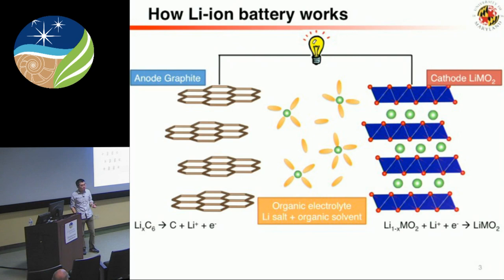So that's one of the mechanisms. The second is that you may have some side reaction. As we showed here, in a solid state battery it's very favorable to have reaction between electrolyte and electrode. In the real commercial electrolyte, the same thing also happens. For example, in the earliest generation of the Nissan Leaf, if they are in states like Arizona, which is super hot, the battery life dies very quickly, like in 2 years. That's basically too hot, so the reaction is accelerated. There were actually some lawsuits there. So as I said, anything that fails will give you failure. There are so many things that can go wrong. It's a fairly complicated system, a battery.